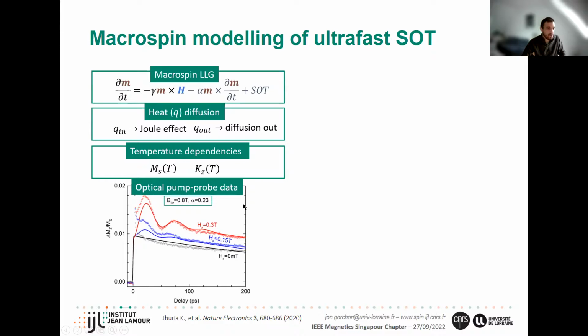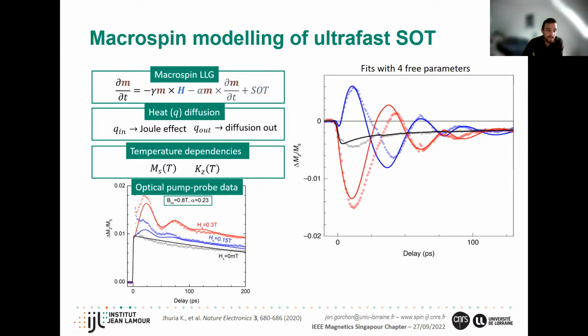We tried to characterize most of the data by doing an optical pump-probe experiment. So we could fit the anisotropy, the damping, and also we could check that our temperature dependencies were okay by doing these experiments at different fluences. And then we could fit the data of the electrical experiment with only 4 free parameters. One which determines how quickly we cool down, which is the interface conductance. And then there's the current density, the field-like, and the damping-like torque that determine the amplitude of these oscillations. And so a very simple macrospin model already fits quite well, not perfectly, the dynamics that we observe.